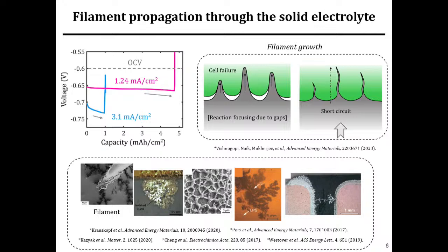Apart from these two mechanisms, a wide range of mechanisms have also been reported in literature, including the growth of lithium dendrites through grain boundaries. The pore connectivity of the solid electrolyte plays a major role in how these filaments penetrate and reach the separator or the cathode. Another key aspect is the heterogeneities or defects present at these interfaces, which can be pre-existing flaws or cracks on the lithium surface. This induces a very important connection between the manufacturing of these metal electrodes and solid electrolytes with the resulting electrochemical and failure mechanisms.